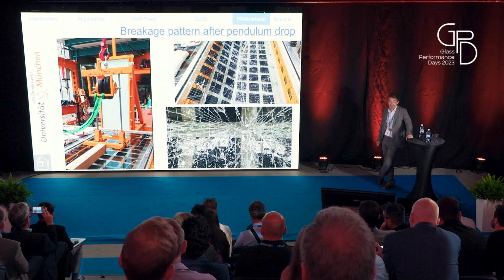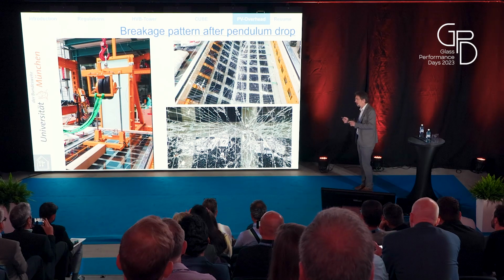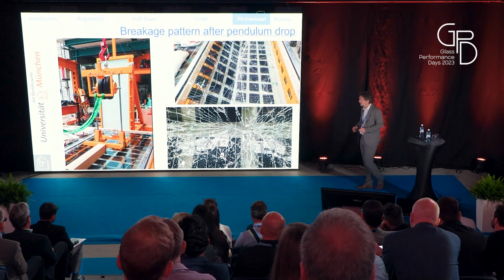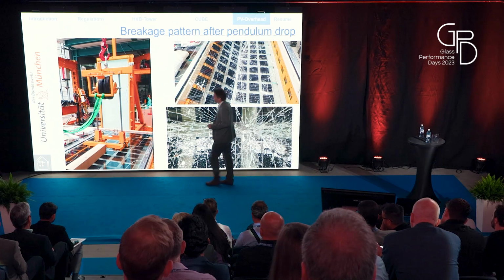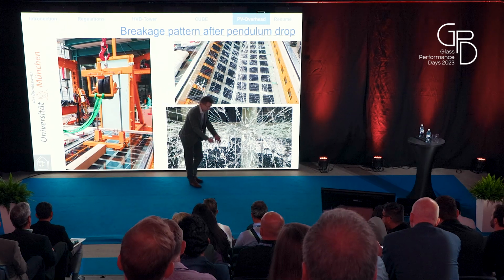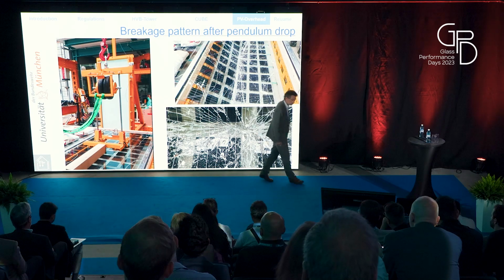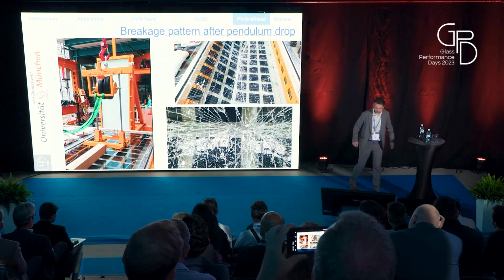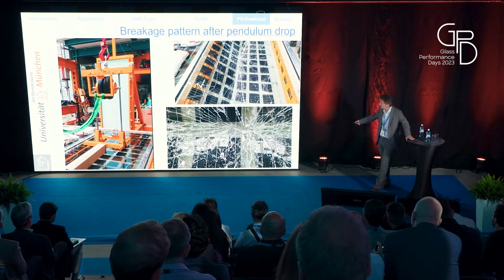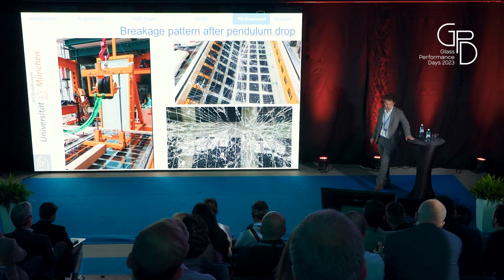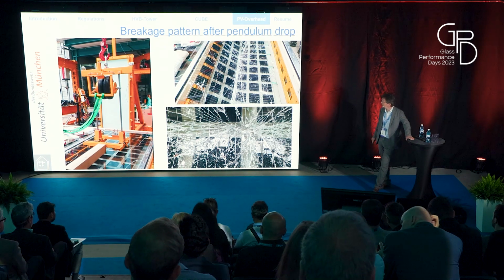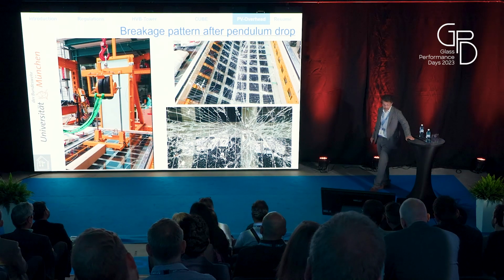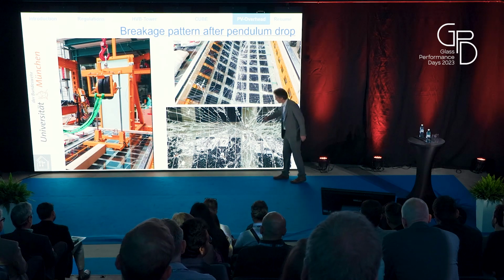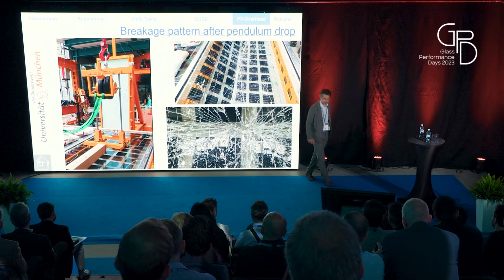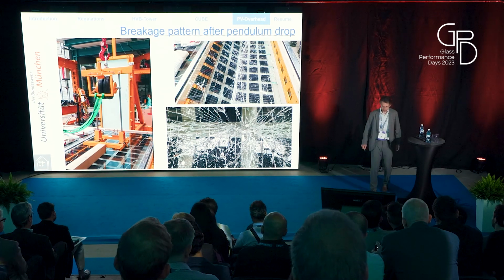So we do additional testing to see whether cleaning while standing on the glass would be possible. This is a standard test you have to do. You throw the pendulum from a height, simulating that the person cleaning the glass falls down, and of course the glass is supposed to stay in place. Because this glass was already broken before, due to the residual strength test, it did not survive. It might have survived with new samples, but the customer didn't want to pay for it. We had our fun, and got some more information about the adhesion, and about the situation if the glass breaks into really small pieces, whether everything is fine or not.